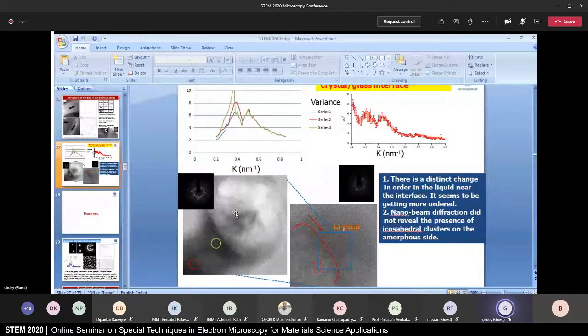Now that we see such small changes in the structure of glass, we can do such a study. So we found that the clusters near the interface are different in structure as compared to the clusters away from the interface. Okay, so before it forms into a crystal, the cluster changes its nature. It's possible that it becomes quasi-crystalline before it becomes crystalline.